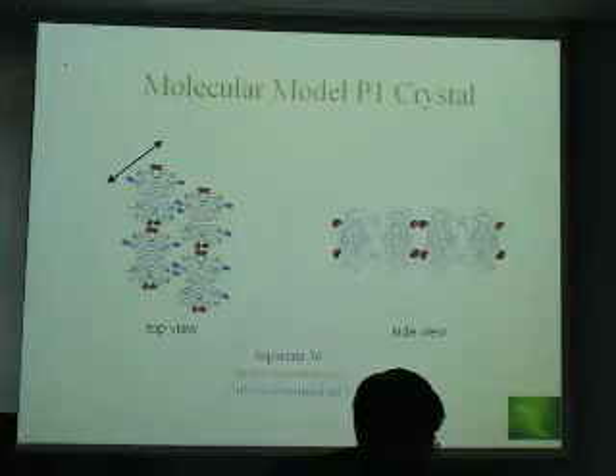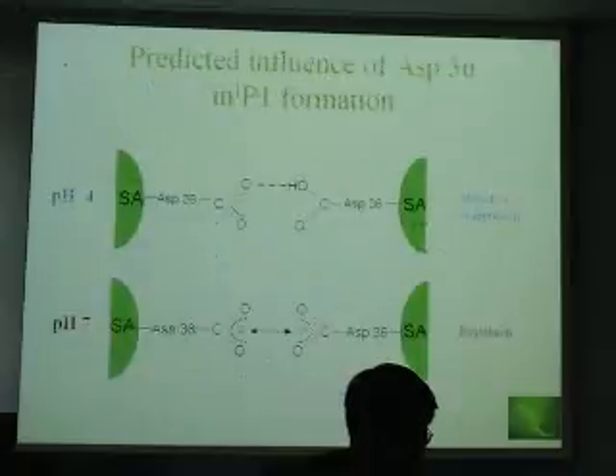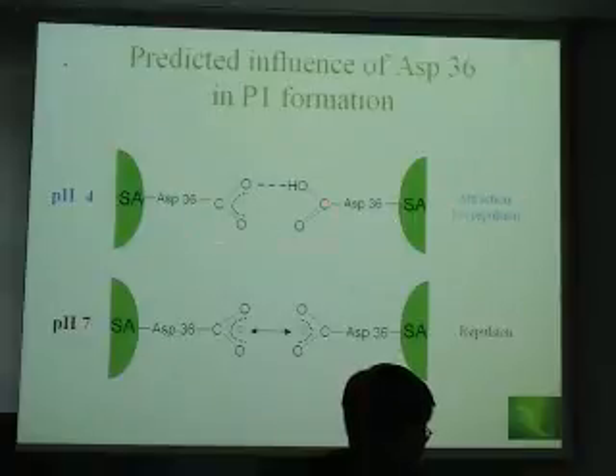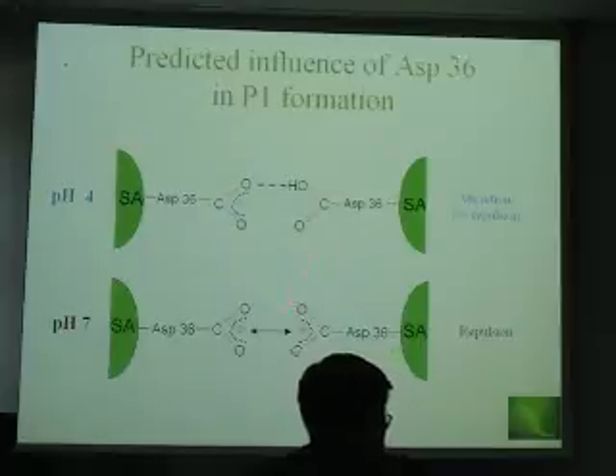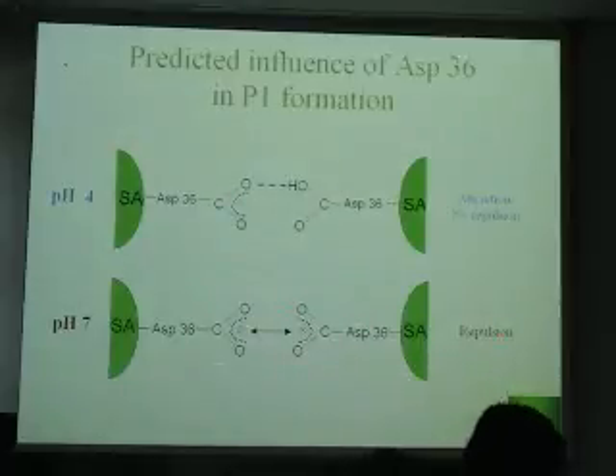We found that aspartate in particular was a good candidate. Both the N groups are also important, but they were not good candidates because they're not well resolved in their molecular structure. So we decided that if we could change this aspartate 36, we could manipulate the interaction in this closely packed structure and see if we understood what was going on. So you'll see there are 4, end on end, there are 4 interactions. If you look on the side view, remembering that it's a tetramer, we have this kind of an arrangement. At pH 4, these aspartate groups should be attracting one another through some hydrogen bonding, and at pH 7 they should be repulsive through electrostatic repulsion.